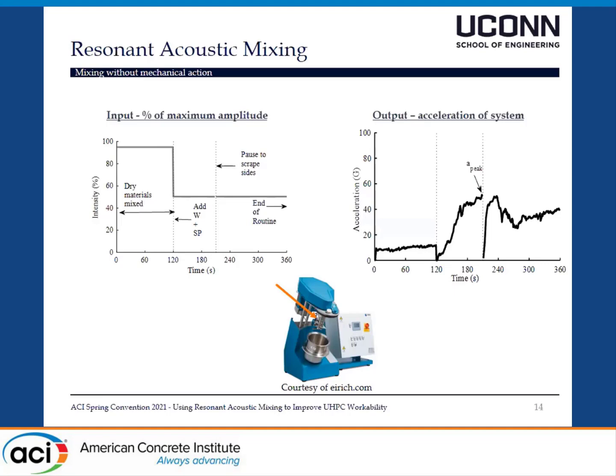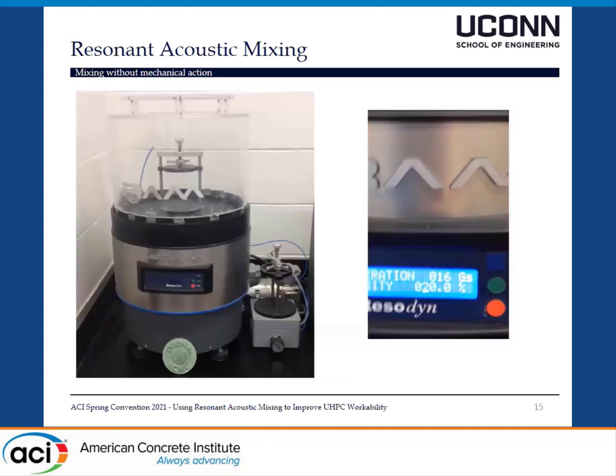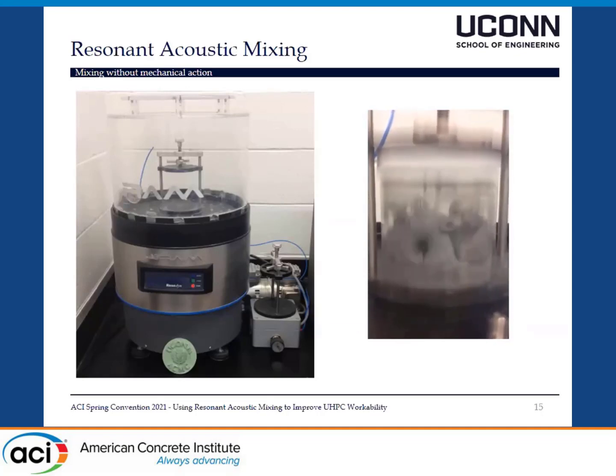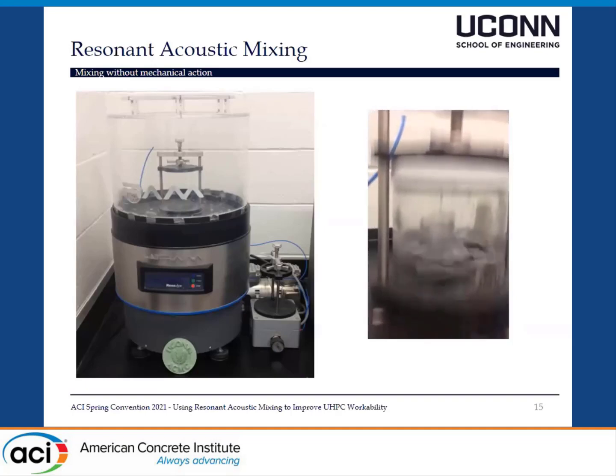So now that we have an idea what the RAM mixer is, can it be used to make UHPC? Here we have a little short video of mixing UHPC. We start off at 20% intensity, which means 20% of the maximum amplitude of this pressure wave. And then by increasing the amplitude to 70% of the maximum, we get to see the various stages of mixing. First we have the dry granulars, then we have the wet granulars, and then as the mix goes higher and higher, you need more power to create that turnover effect. And you'll see instantly in this video the exact moment where we can see that all the particles are mixed precisely. And this helps in